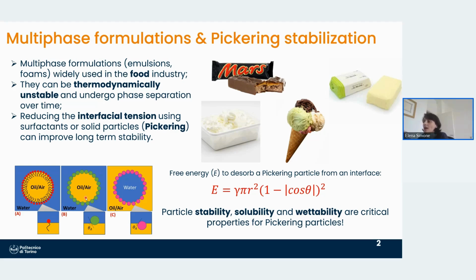Pickering particles are solid particles that provide very stable formulation, and depending on the nature of the particle, we can stabilize an oil in water or a water in oil. So if we look at the absorption energy, so how strongly a particle can absorb at an interface and provide stabilization to a structure, we can see that this depends on the size of the particles and also on the three-phase contact angle, which is basically how hydrophilic or hydrophobic is the nature of my particles. So hydrophilic particles would be more suitable to stabilize oil in water. Hydrophobic would be more suitable to stabilize water in oil.